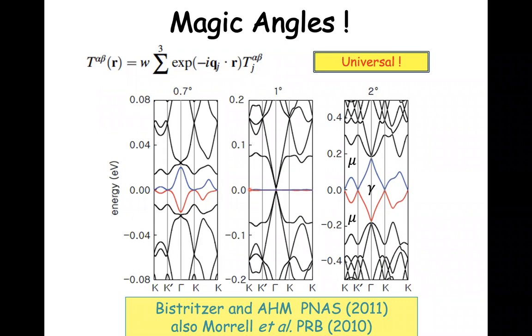And we know when we slow electrons down, then their physics will be controlled by electron-electron interaction. So that was already obvious at this time. What was not obvious at all is that it would be possible to actually prepare 2 graphene sheets with this magic twist angle, and that's what was achieved experimentally.